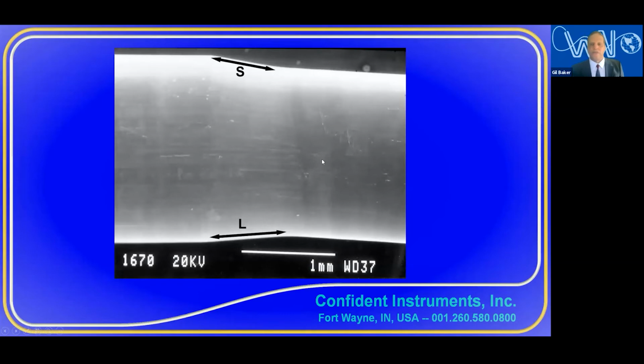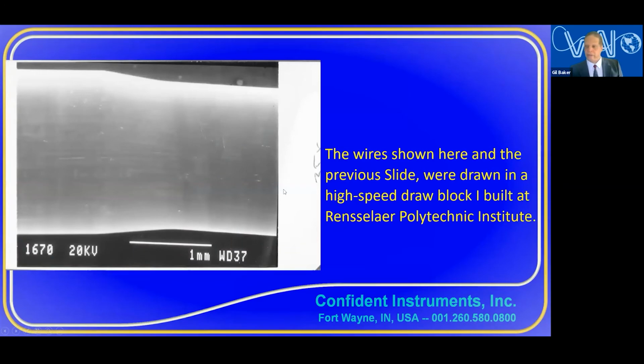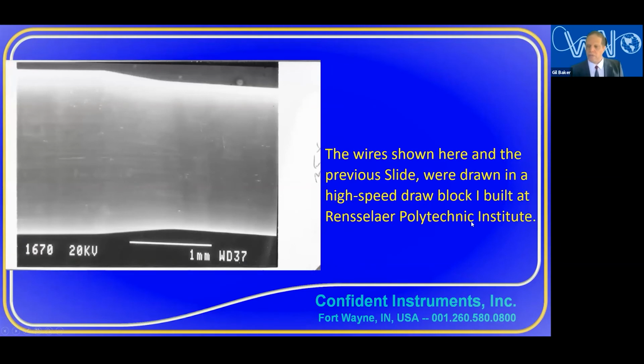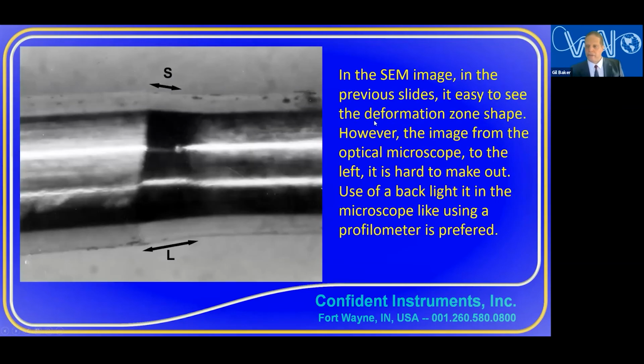And here are some examples of wires that are asymmetric in their deformation zone. Here's a SEM picture, and we put on two values we use to measure the asymmetry that's in the article. Let me just say these were drawn in a high-speed draw block I built at Rensselaer Polytechnic Institute. And here's an image on the optical microscope. So I recommend backlighting in the optical microscope because it's harder to see than in the SEM. But again, we use this S and the L, S for short and the L for the long.